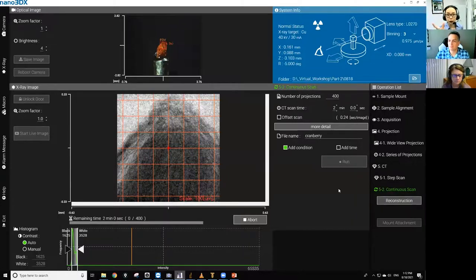For the width, you can do what we call an offset scan, meaning that there is a way to maximize the detector size: you look at half of the sample first. Then when the sample rotates the other way, you look at the other half of the sample. This is a complicated one to explain by talking about it, but you can effectively double the detector size to cover the entire width of the seed. Then with that offset scan, you do probably top, middle, and bottom, or top and bottom halves, and merge the resulting scans afterwards to have the entire seed scan.